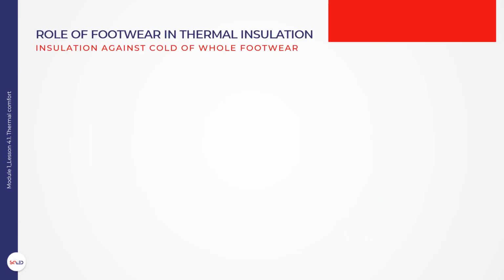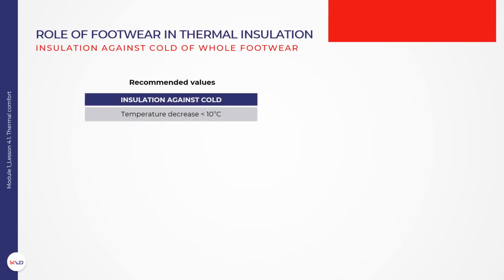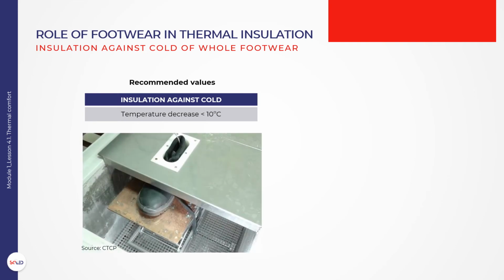Test methods are available to evaluate the insulation of footwear against cold. In this test, the footwear is placed on a copper plate inside a cold chamber at a very low temperature, for example at -17 degrees Celsius for 30 minutes, and a temperature sensor is placed inside the footwear to record the temperature drop. The temperature decrease on the surface of the insole should not exceed 10 degrees Celsius.